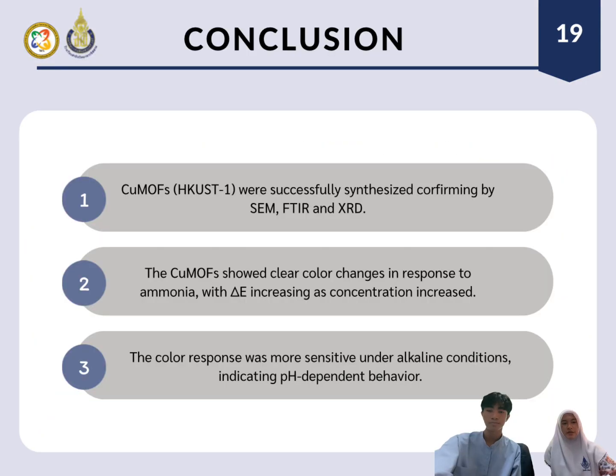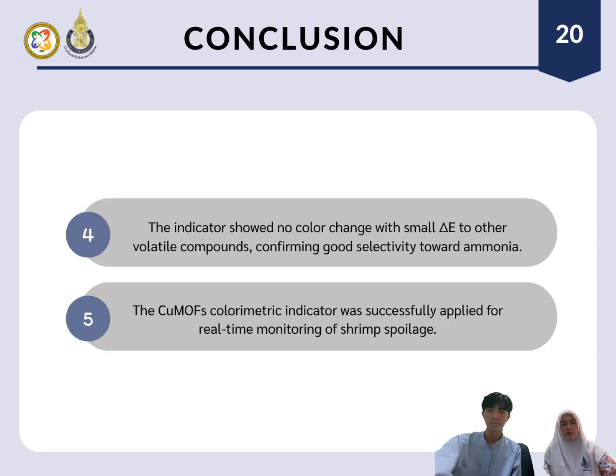For the conclusion, first, copper MOF was successfully synthesized, confirmed by SEM, FTIR, and XRD. Second, the copper MOF showed a clear color change in response to ammonia, with delta E increasing as concentration increased. Third, the color response was more sensitive under alkaline conditions. Fourth, copper MOF has good selectivity toward ammonia. And last, the copper MOF colorimetric indicator was successfully applied for real-time monitoring of shrimp spoilage.